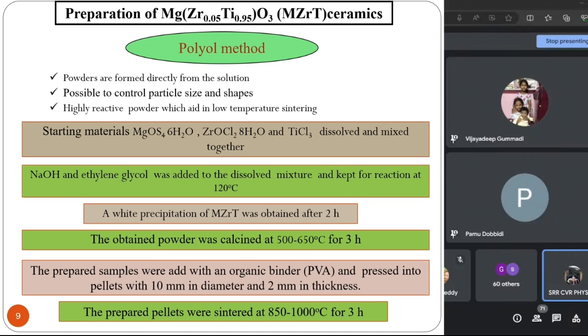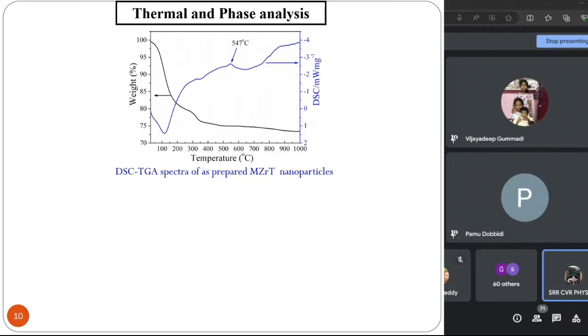Why did we choose a polyol method? In the previous slide, we have seen they are all using a solid state reaction method. When we use a solid state reaction method, the material will go into a bulk state. That's what we don't want. If we go that way, there is no advantage to reduce the temperature. That's where we started with a low temperature processing method, which is called the polyol method. We slightly modified this method and did this work. Can you go to the next slide, please?